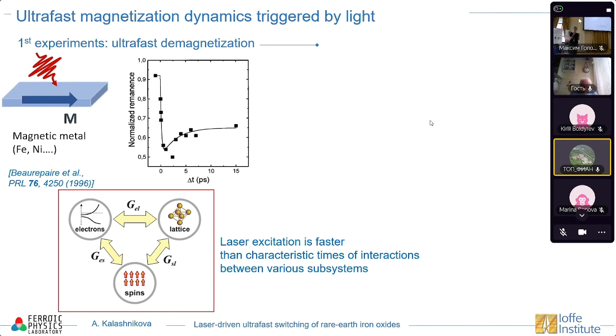This effect is still a matter of really hot debates and discussions. More and more sophisticated and advanced experiments are performed to really understand this process. But so far, it is the general understanding that all ultrafast laser-driven magnetization dynamics relies on the fact that our laser pulse is so short, and the processes which the laser pulse excites in the material happen on such a fast time scale, that it appears to be shorter than some characteristic time scales within the material, like electron-phonon coupling or spin-phonon coupling, and so on and so forth. And since we really bring the material to some non-equilibrium state, very interesting processes start to happen which are not possible with longer pulses.